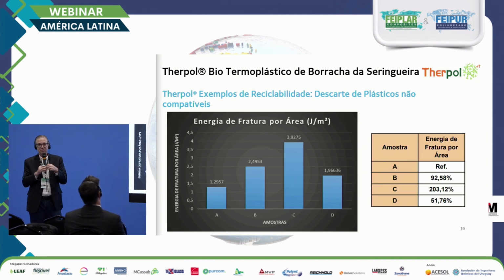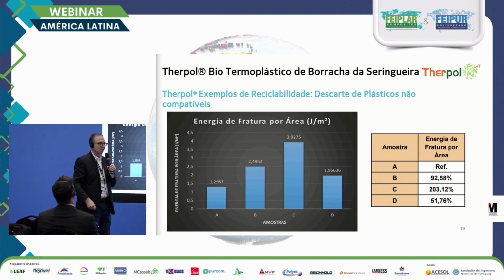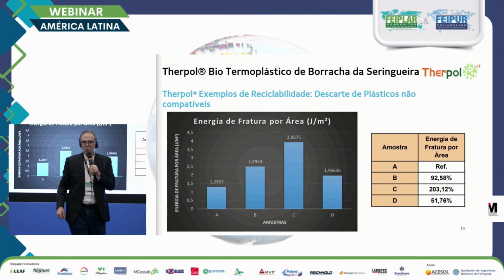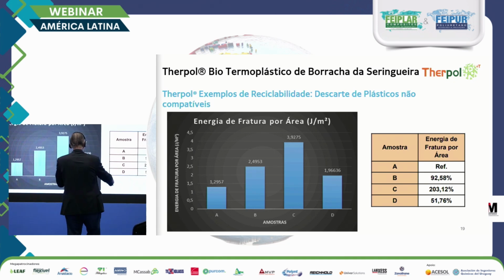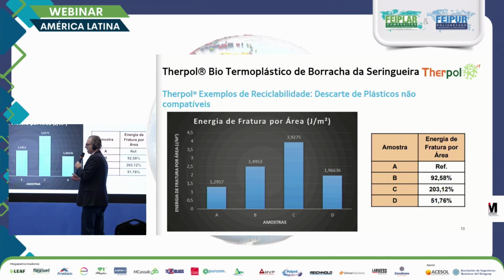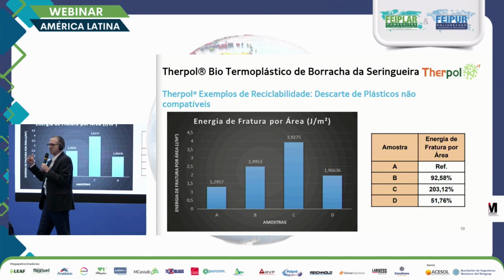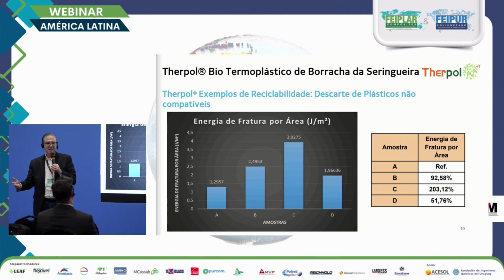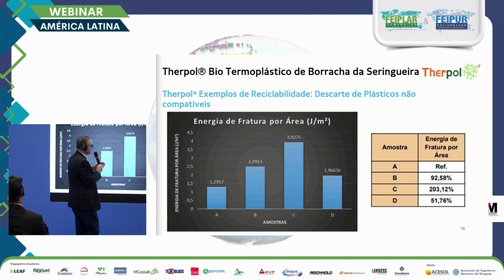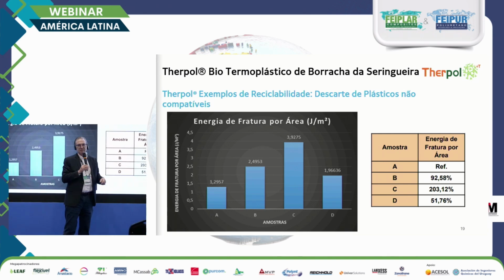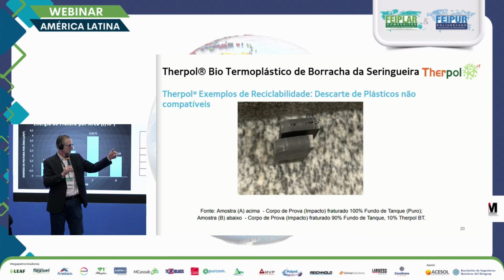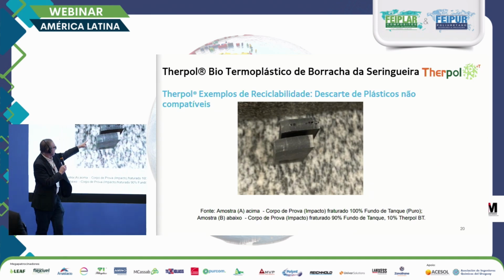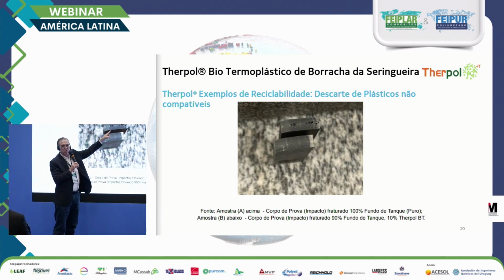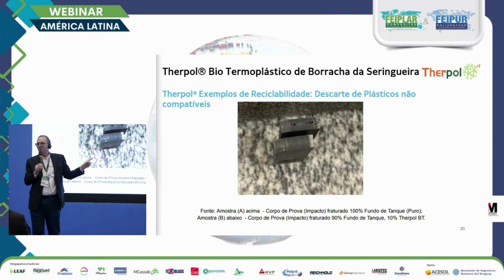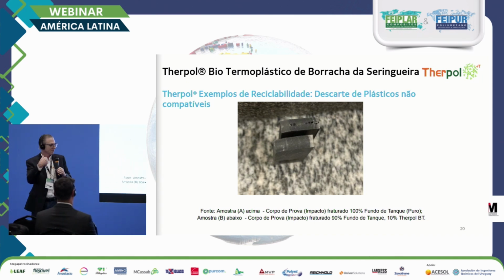And on the next slide, which is the impact, resistant to impact, it means whacking the plastic to see if it breaks. When we added the best combination, which is C, 40% of the tank bottom, 50 of recycled PP, and 10 Terpol, it increased 200% the resistance to impact, because we don't have these little holes anymore. This sample is at the fracture without Therpol. It was porous. With Therpol, it wasn't porous and increased resistance.